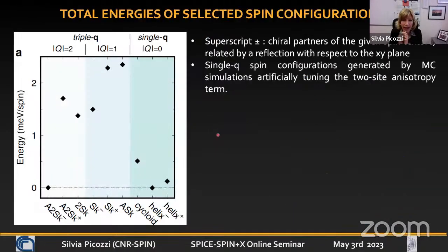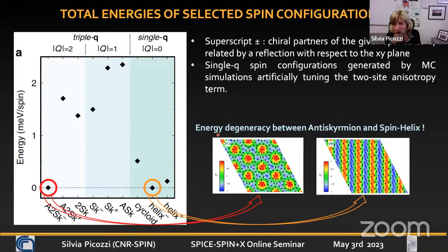Okay. So I should say, actually, that the mechanism is there. We believe that if you have a large anisotropic exchange, then you can really have this anti-skyrmion. What I cannot say is that NiI2 is a system where you really have this as a ground state. Because, for example, if we evaluate the energy of this anti-skyrmion, and also the energy of a spin helix, they are basically degenerate. So by DFT we cannot really distinguish between them. So my message would be more about the mechanism than about its realization in NiI2.